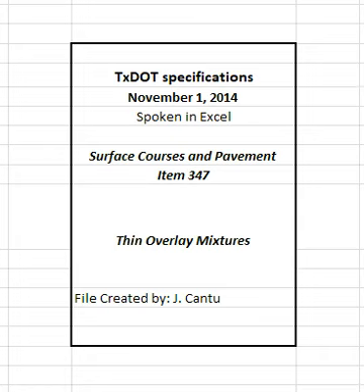2.1.3 Fine aggregate. Fine aggregates consist of manufactured sands and screenings. Natural sands are not allowed in any mixture. Fine aggregate stockpiles must meet the gradation requirements in Table 2. Supply fine aggregates that are free from organic impurities. The engineer may test the fine aggregate in accordance with TEX 408A to verify the material is free from organic impurities.